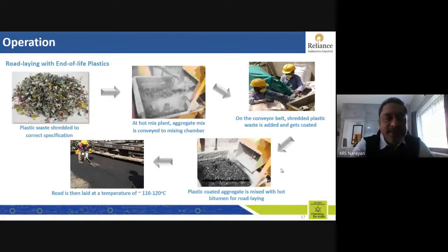The operation is basically, as I said, you have to segregate it, and then you will have to shred it as per size. A lot of machinery. This is a very, very cheap process. You will get a shredder within a lakh or 2 lakhs of money. You can shred up to 2 to 3 metric tons per day with these shredders. So they are shredded as per the specification, because the size of the aggregate is very, very crucial for the performance of the road.